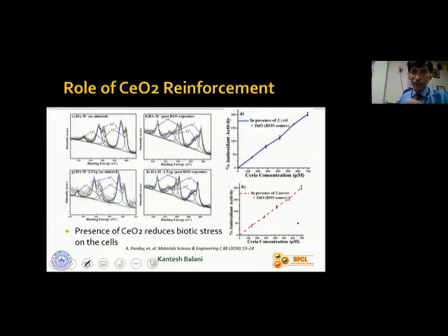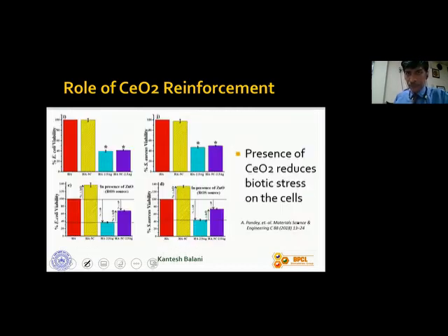So you also have a presence of cerium 3+. That is becoming cerium oxide, CeO2, with 4+ by taking up extra oxygen. Now we're going from Ce2O3 to CeO2. That part we could establish via XPS, X-ray photoelectron spectroscopy. Again, we could establish the excess oxygen being taken up by this particular system, in comparison to without ceria and then with ceria.